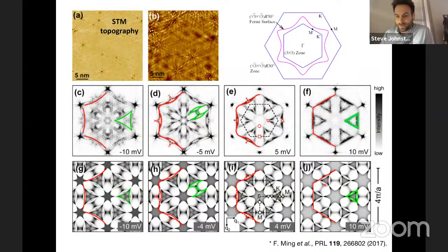The calculation here is predicting that you have these triangles that are warped, but the experiment's seeing a very strong flattening of these triangles. So how is this even possible? You know, if you have a doped Mott insulator, if this is really a Mott insulator, you put 10% doping. How can that be weakly correlated? It's very hard to believe this. I mean, I don't know.